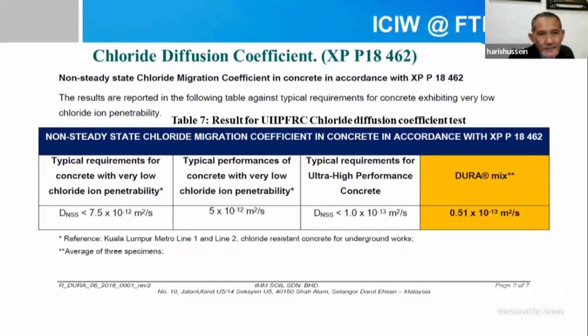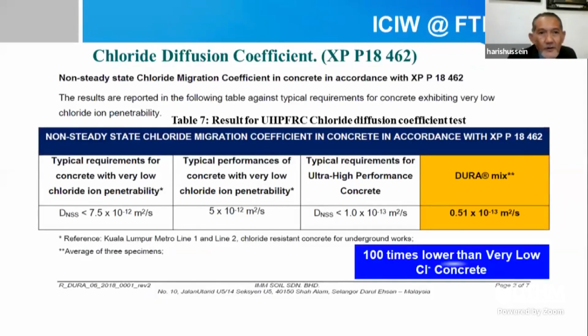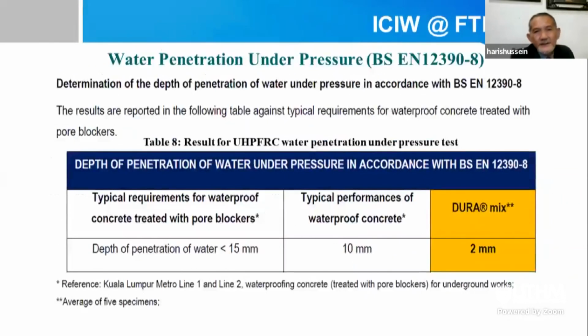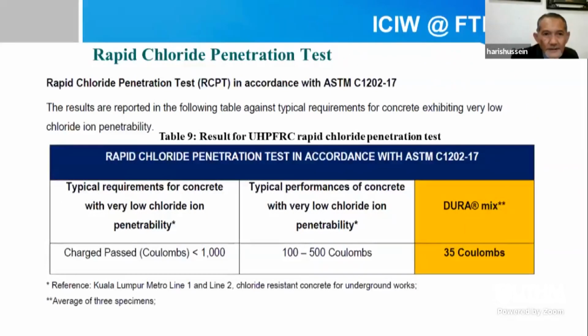Durability tests were also carried out, one of which is the chloride diffusion coefficient. The result for ultra high performance fiber reinforced concrete is much better compared to the normal concrete used for structural components. Similarly, for water penetration under pressure, it is only 2 mm compared to normal concrete of 10 mm. Rapid chloride penetration test for ultra high performance fiber reinforced concrete is 35 coulombs compared to normal concrete of 100 to 500 coulombs.